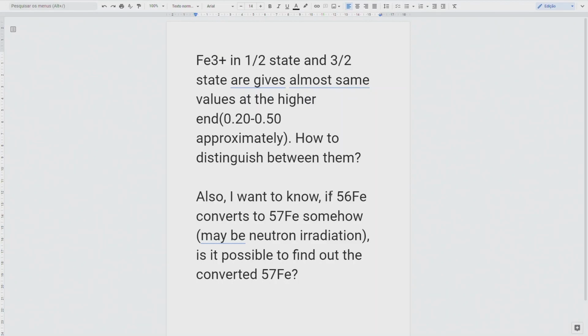Please, could you repeat? I think from the question that she wants to find out if you can distinguish the converted iron 57 from the original one. Maybe for some people, iron 56 is totally mute. So you can wait 2 years, you will not obtain a spectrum. You can obtain a spectrum only with iron 57. Suppose that you have a metallic iron with 2% of iron 57. So you have the fraction from Mossbauer.